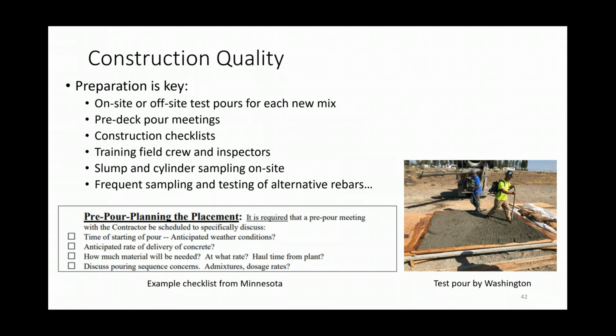For example, people use these test pours on the right-hand side. I give an example from Washington. This is a test pour of a new mix. It could be on-site or off-site, but if the contractor does a test pour, they know what to expect with that, the rheology of that mix and workability of that mix. Pre-deck pour meetings, construction checklists. On the left-hand side, I have the example checklist from Minnesota for a pre-pour planning the placement checklist. There's other ones. And of course, training people.